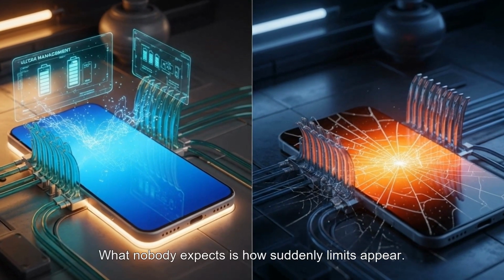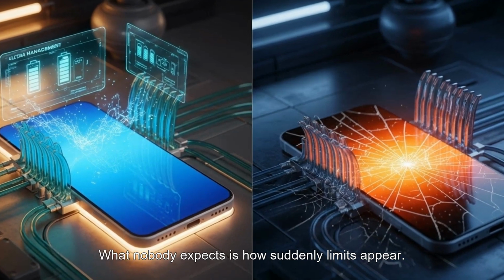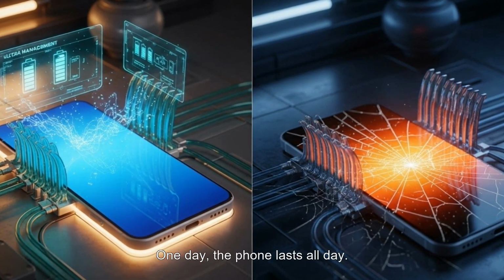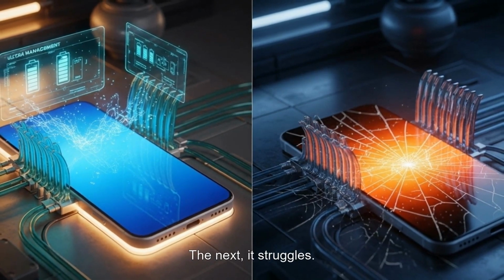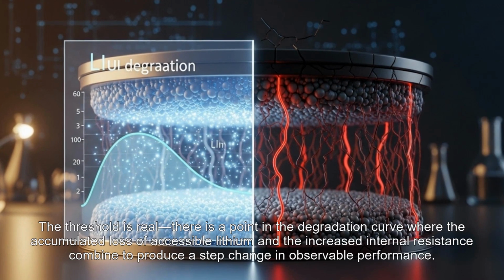What nobody expects is how suddenly limits appear. One day, the phone lasts all day. The next, it struggles. The chemistry did not change overnight. It crossed a threshold. The threshold is real. There's a point in the degradation curve where the accumulated loss of accessible lithium and the increased internal resistance combine to produce a step change in observable performance.